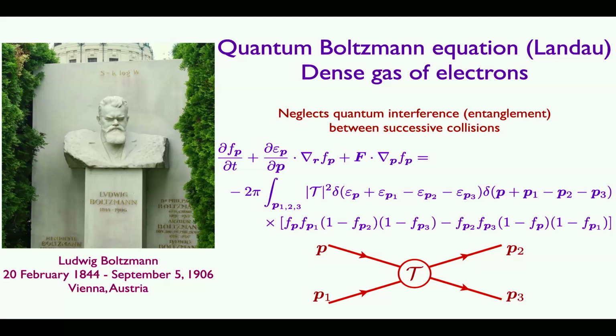But the remarkable thing, as emphasized by Landau much later, is that the Boltzmann equation applies equally well for a dense quantum gas. And the reason are these factors here, these 1 minus f factors on the right-hand side, which impose the Pauli exclusion principle. And the effect of these 1 minus f factors, which are absent or really equal to 1 in a classical gas, is that collisions in a dense quantum gas are rare, because any particular single particle quantum state is either empty or full. If it's full, then this 1 minus f is 0. If it's empty, then the f is 0.